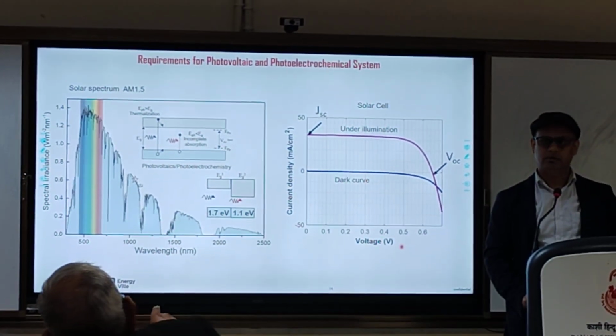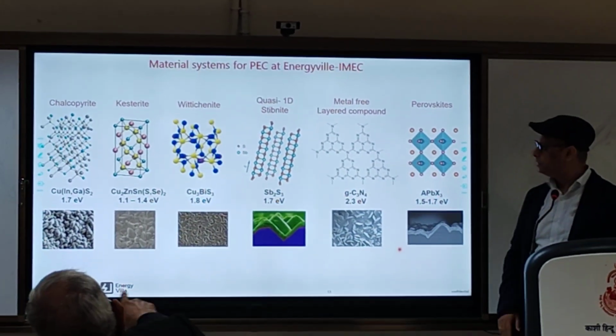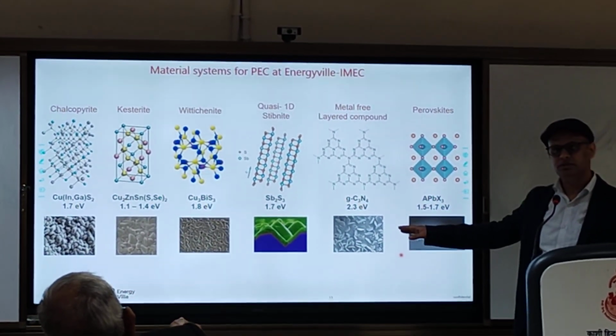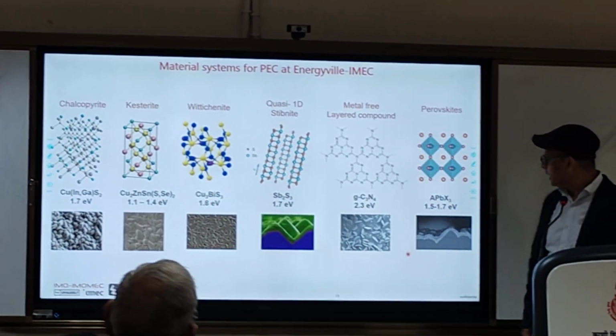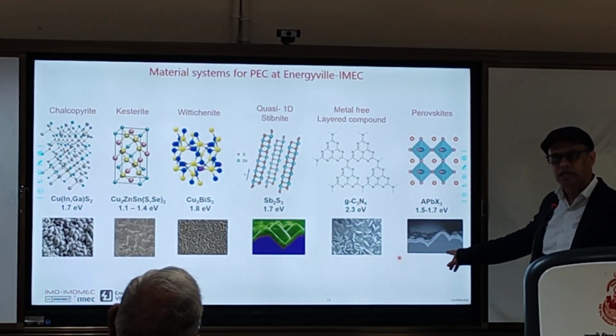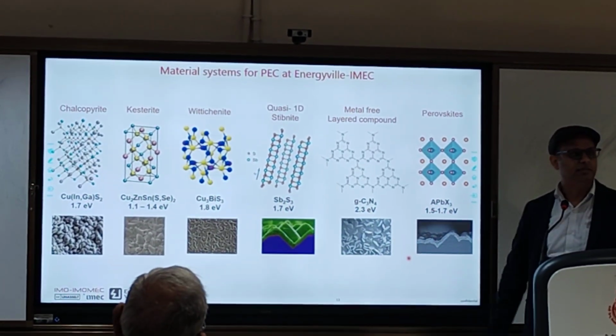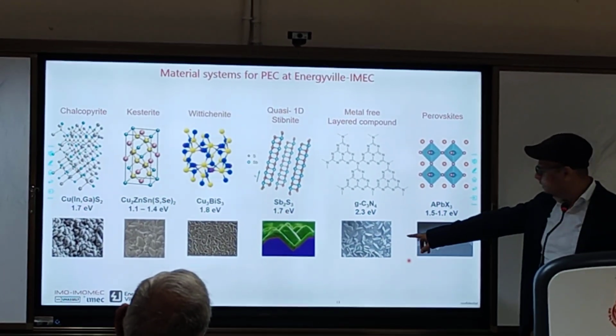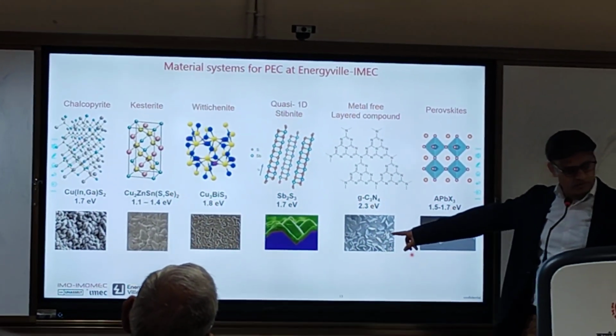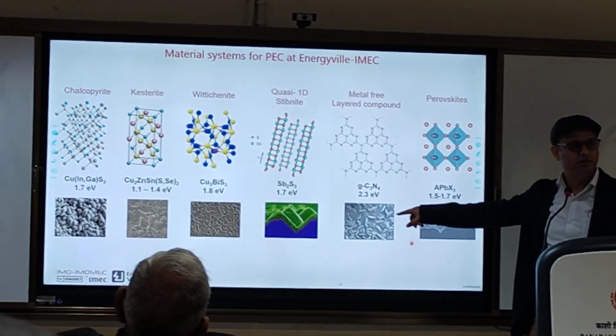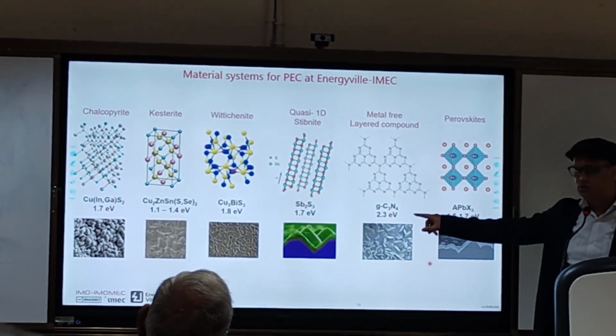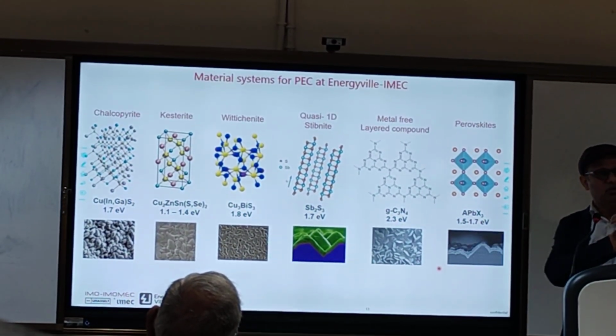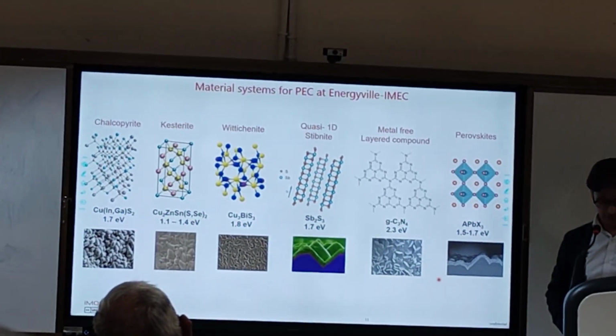Now, you were showing on the board, right? This is the SEM image? Yes, please excuse me for not putting the scale bars over here, but this is an SEM image. Different morphologies. This one is particularly interesting because this is coated on silicon. The blue is silicon, and on top what you see is antimony sulfide. So it's a monolithic tandem that we developed very recently.